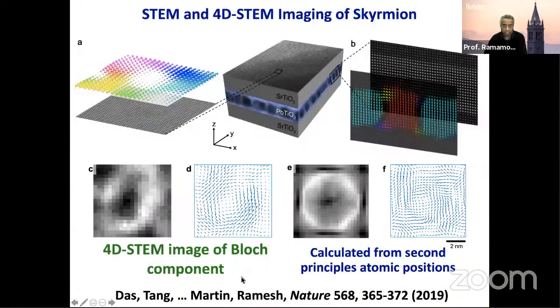Again, David Muller and his student did a fantastic job of doing 4D STEM imaging. And that's one image of the skyrmion, the Bloch component in plane. That's the vector mapping for the Bloch component going counterclockwise. This is the theoretical calculation from second principles. This is the image that you calculate. That's the vector pattern. All seems to fit very well.